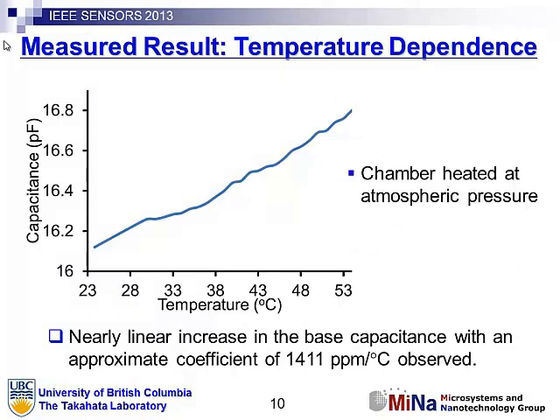is indicative of one difficulty with this sensor, which is that it was highly temperature dependent. So its base capacitance varied quite strongly with temperature. The primary reason for this is that the dielectric we use is Parylene-C, which has a high dependence of dielectric constant on temperature. So in our biomedical application, there's a fairly narrow temperature range, but this is not good enough. So one idea is to use Parylene-N, which has a much lower dependence on temperature. Maybe there are other things we can think of to reduce this kind of dependence and just isolate the pressure dependence of the sensor itself.